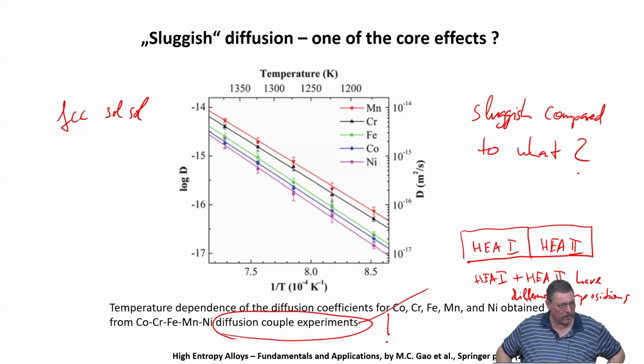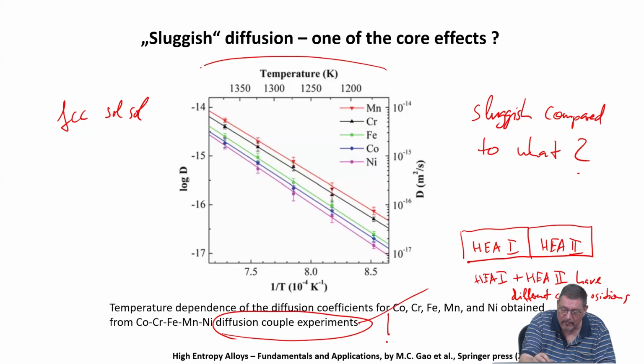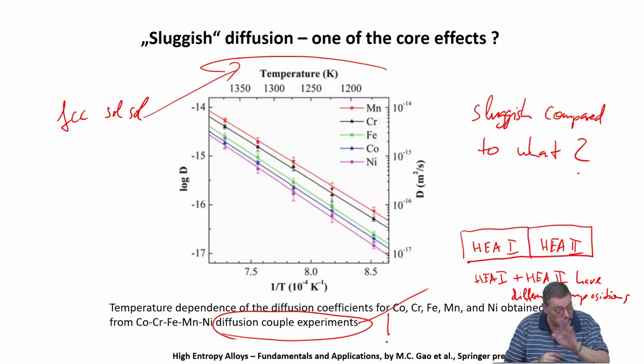But if you go to lower temperatures and wait for a sufficiently long time, you will see additional phases form. But here they have confirmed that it was a single phase solid solution. In all these temperatures here, single phase solid solution. But if you go to lower temperature, absolutely other phases form, like sigma phase. But sluggish diffusion means, from this plot we don't know what it means, right?